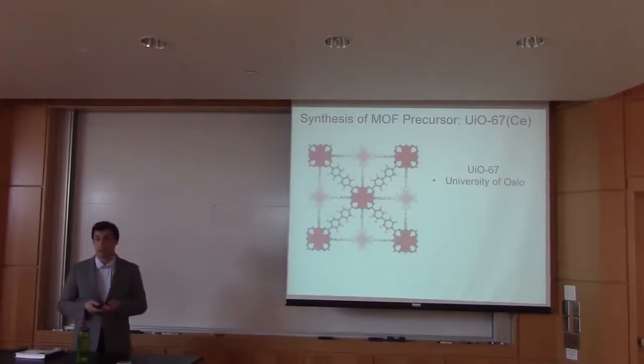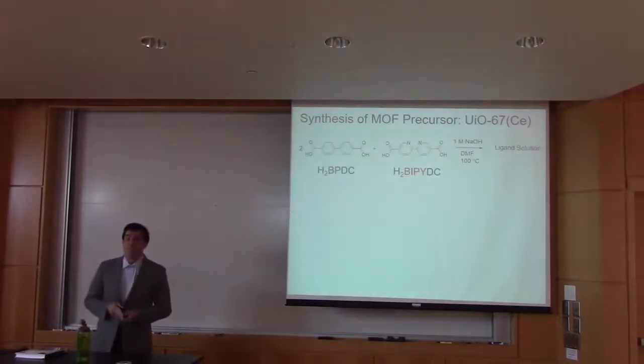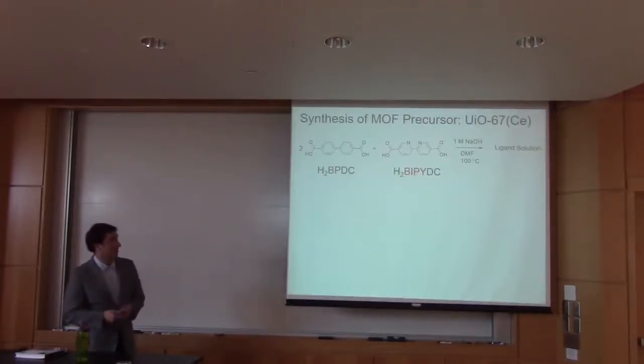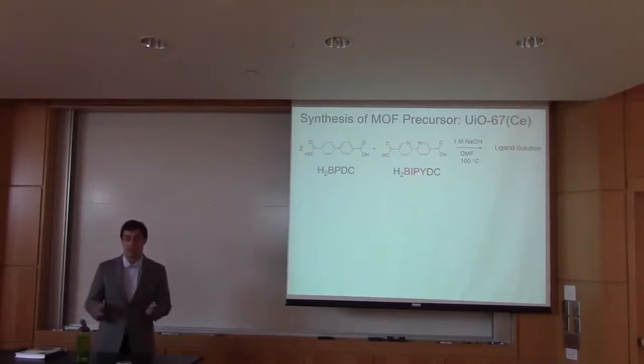And it's normally a zirconium MOF, but since we've changed it for cerium, we just wanted to note that and any future changes. Now this synthesis is the easiest I've ever done, and it's never going to get this easy again, which is a little disappointing. I used these 2 linkers that I showed earlier, the blue cylinder and the red cylinders respectively, which is the biphenyl and the bipyridine dicarboxylate. We're using that in a 2-to-1 ratio. Adding it in base, the sodium hydroxide, to deprotonate these carboxylic acids, which allows them to bind to those metals.